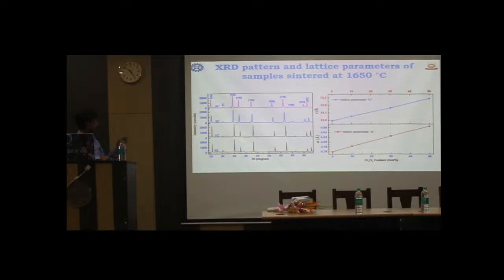You see the peak is shifted towards the eskolaite side, that means to the left, to a lower 2 theta angle. The eskolaite is at a lower 2 theta. And from the Rietveld analysis, if you calculate the lattice parameter, it is a linear relation. So that means there is a perfectly ideal solid solution, and if you increase the Cr2O3 content, the lattice parameter will increase.